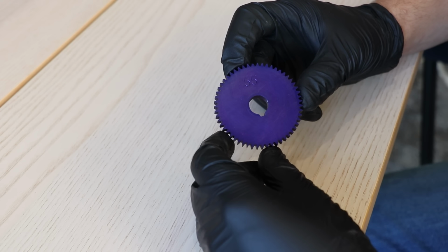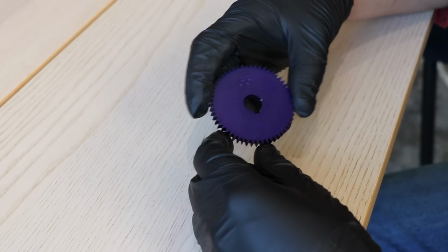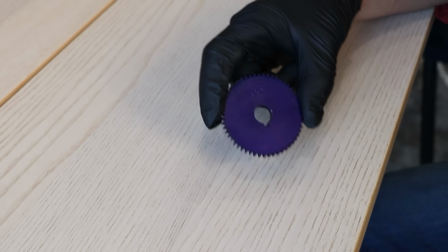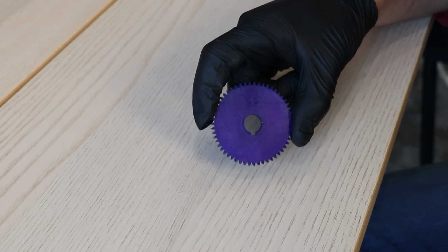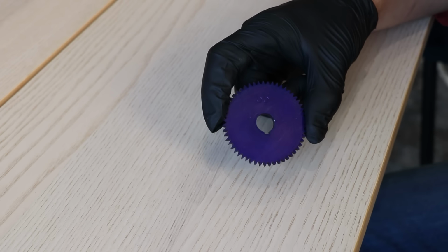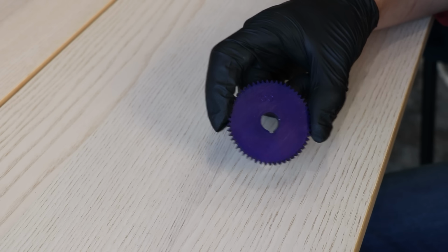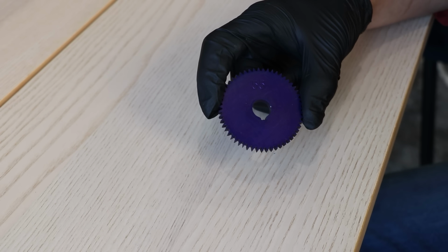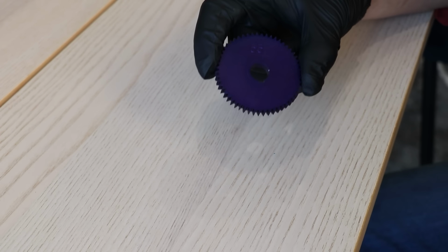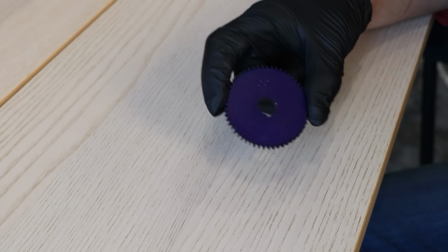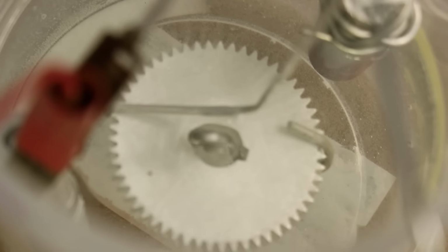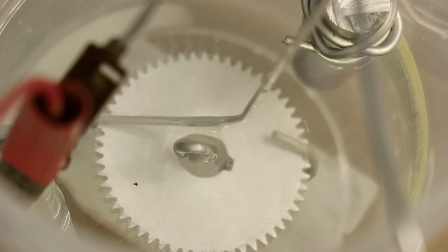There's still certainly room for improvement, but as far as anodizing goes, it's about as good as I've ever gotten it. And for basic parts, which are just for show, this is more than good enough. Honestly, really happy with it, and I'm really happy that I was able to do all this for less than $50 all in, and I didn't have to worry about getting sulfuric acid. The sodium bisulfate seemed to work pretty well without any major issues.